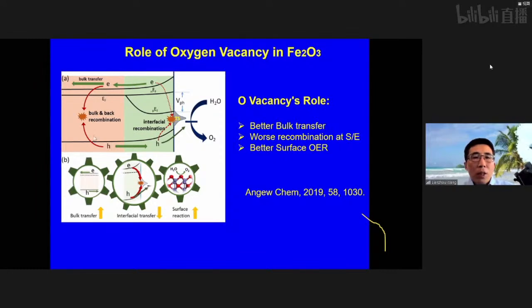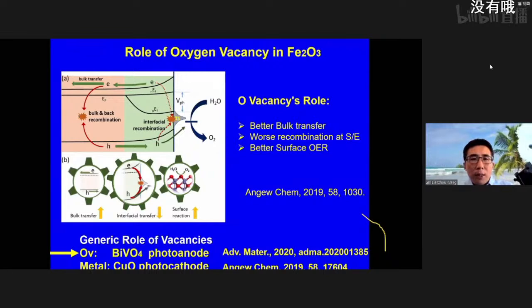And overall, in the bulk, it's good, and on the surface it also has a good role, but in the middle it really has some damaging role, and we really need a very good balance to modify the electrode by tuning the oxygen vacancy position and also the composition. So we also extended our study to some other systems, like a bismuth vanadate electrode and also the photocathode, and we also found consistent roles of vacancy control